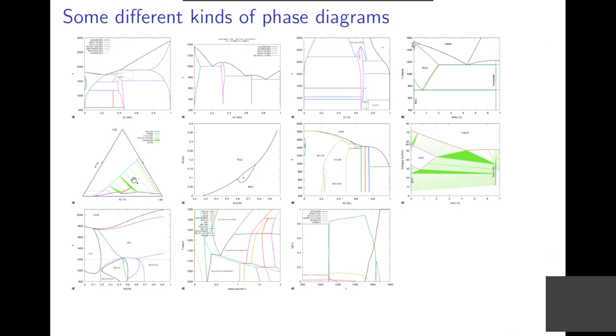You can choose. And here you have an activity rather than the composition. And the sigma phase here is the one you have in the middle here. And the two-phase regions become a line because you have the same chemical potentials in the two-phase regions here. And here you can see the meaning of the node point. If you start the calculation here, you will find the sigma phase. And that is a node point here.